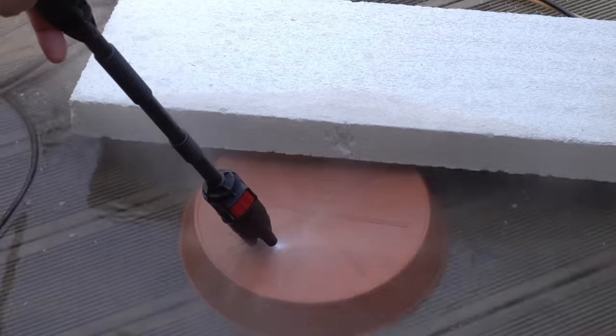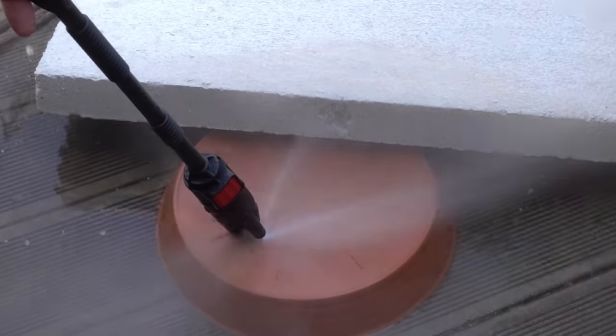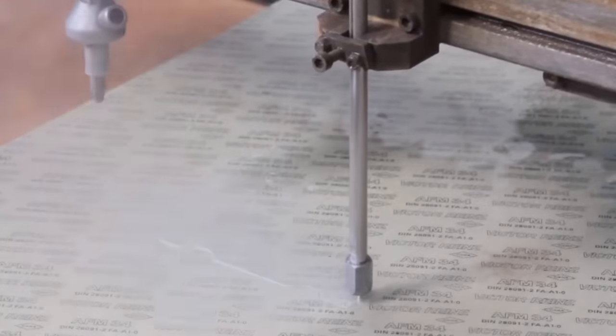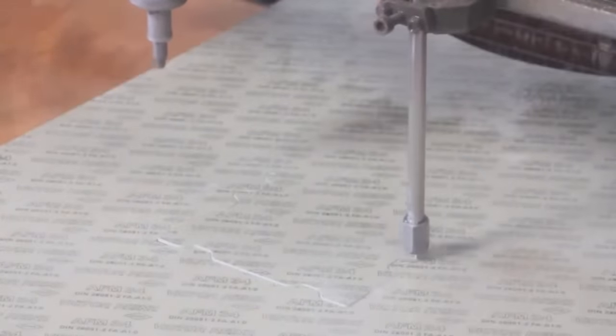But nonetheless, this does give you a realistic visualization of what a leak in a sub at depth would look like. And that faced with the soft material like plastic, a hair-sized leak would rapidly transform into, first of all, a millimeter-sized leak, and then a centimeter-sized leak. Which brings us back to, what is the most likely source of such a leak?